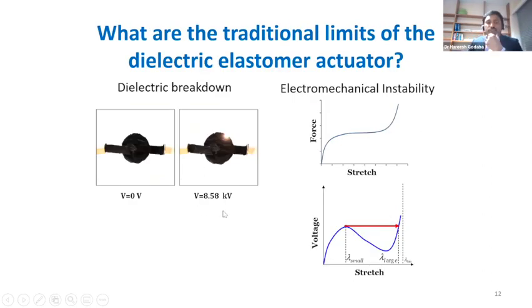And what we have seen is that the traditional limit for dielectric elastomer actuator is related to this breakdown, but it's related in a sort of peculiar way. When the force stretch curve is non-linear like this, then the corresponding voltage versus stretch, or the voltage versus expansion curve, looks something like this. It is an N-shaped curve. So now when we slowly apply the voltage, the stretch will continue to increase until it comes to this peak of this N-shaped curve.